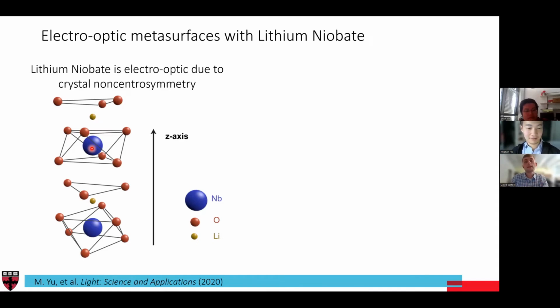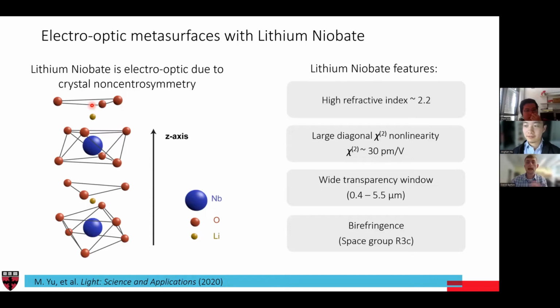And so what this means is that this material is electro-optic, and it's also a ferroelectric material because it is not actually centrosymmetric. And actually, it's a very useful material because it has a relatively high refractive index, so we can do a lot of engineering with it. It also has a very large chi2 nonlinearity, and for its electro-optic response, this parameter is very high for materials that we can grow and use efficiently in deployable products.